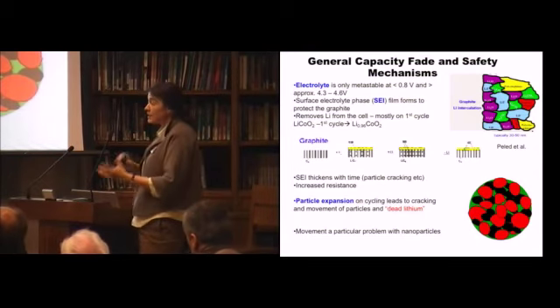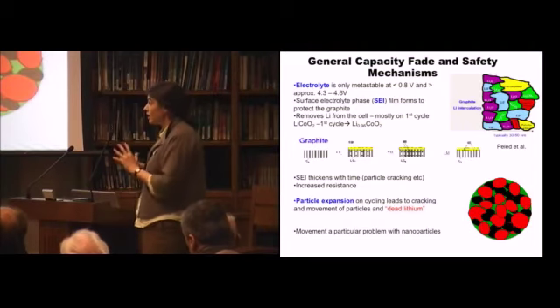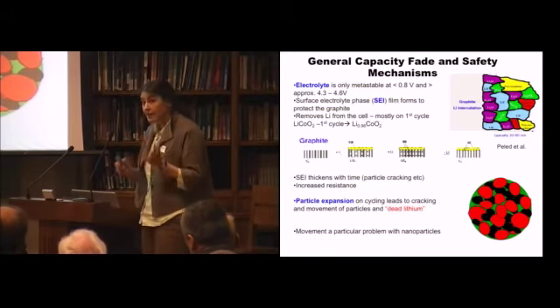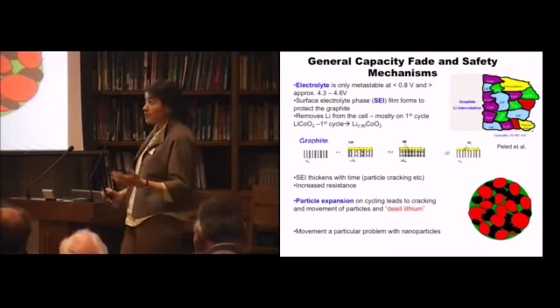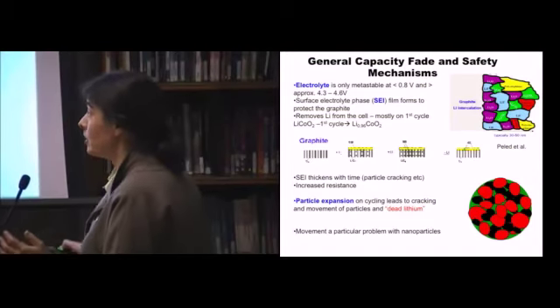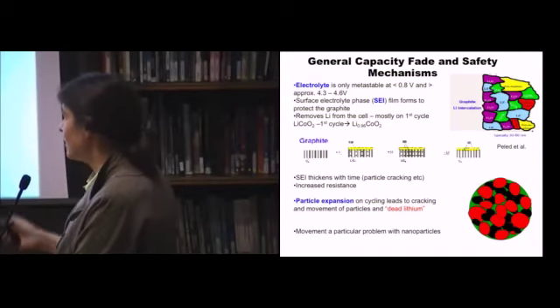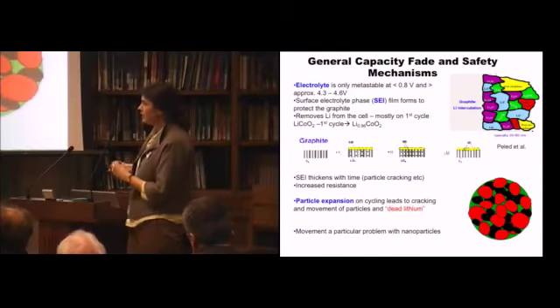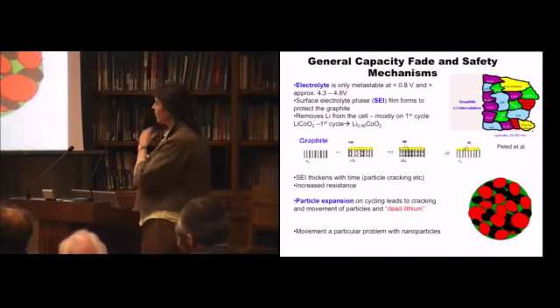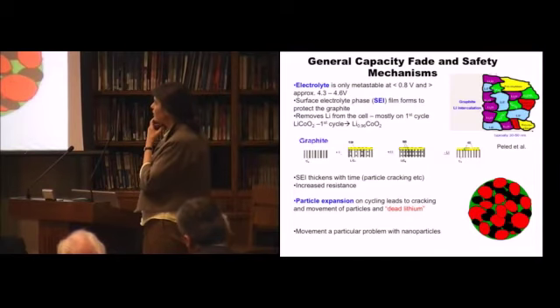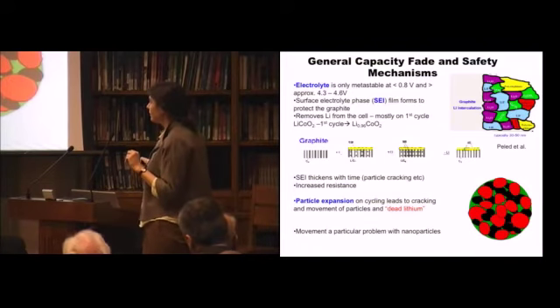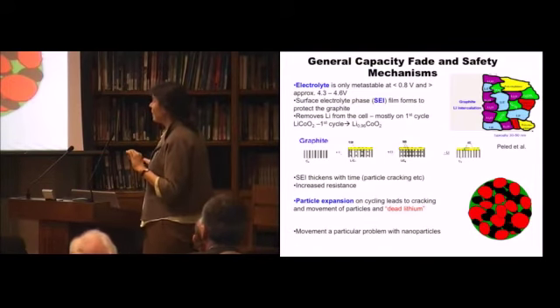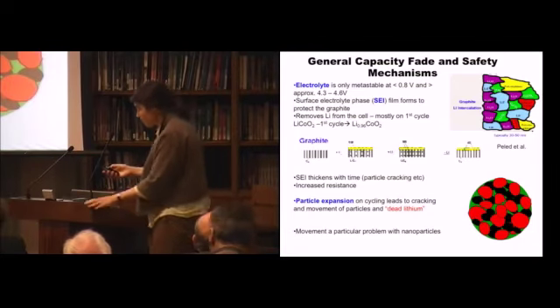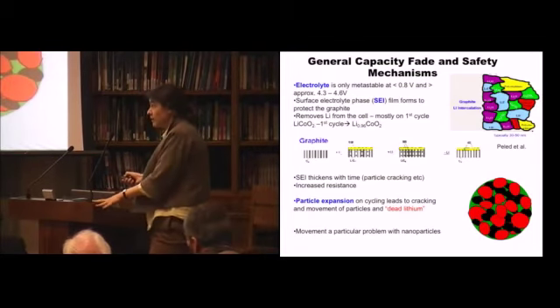And so over time, as this graphite is expanding and contracting, you can get particle cracking and increased formation of your SEI. The SEI can fall apart, the battery can overheat, and you can get increased decomposition, and the battery continues to fail. This particle expansion I was telling you about can result sometimes in loss of contact between your particles and the carbon, so that you can get what's known as dead lithium. So these are particles within your composite that you can't actually contact electrically. And so over time, this can be another reason that batteries fail.